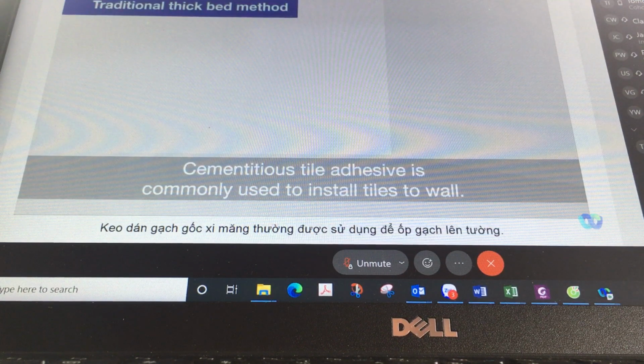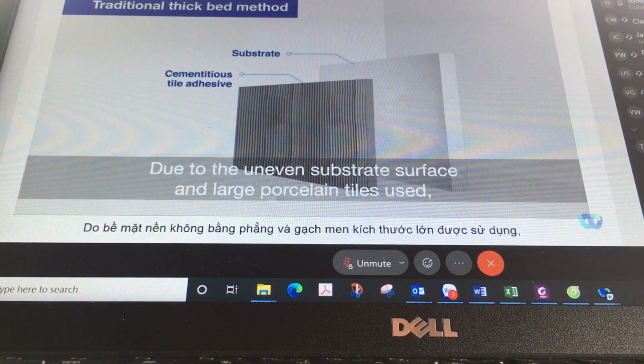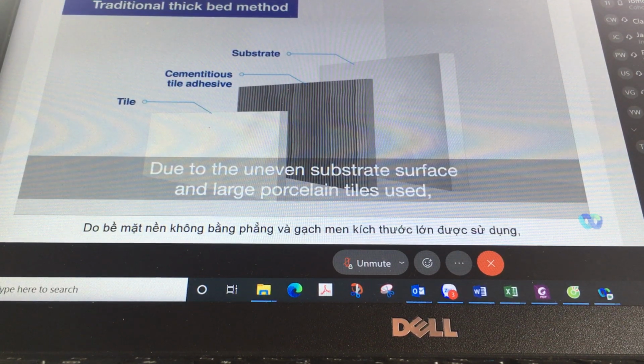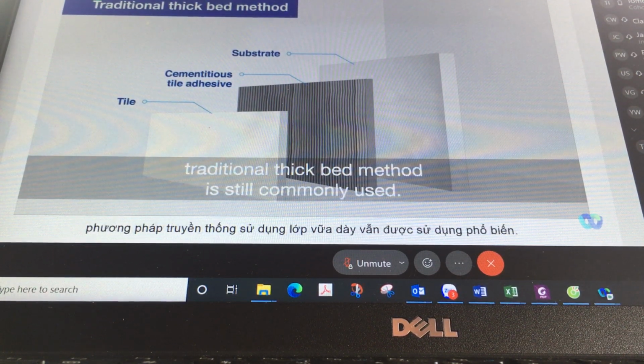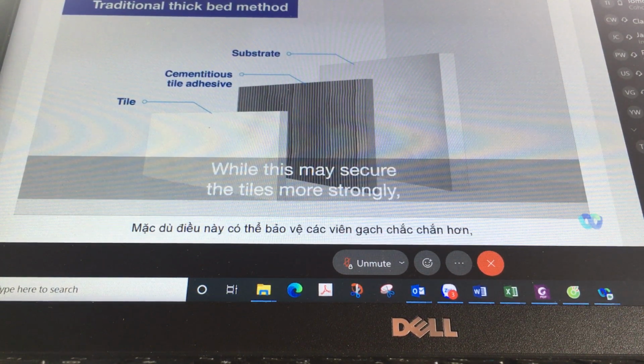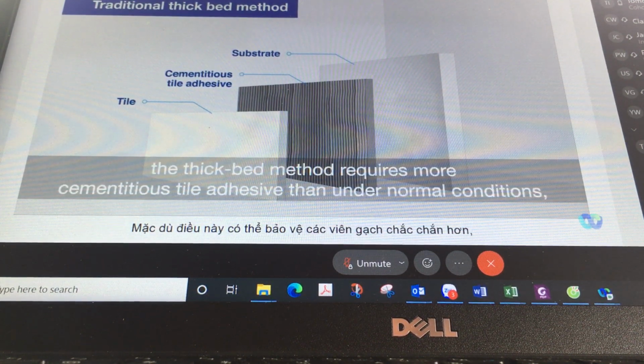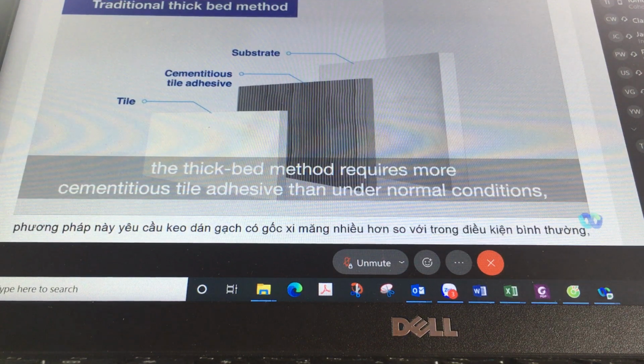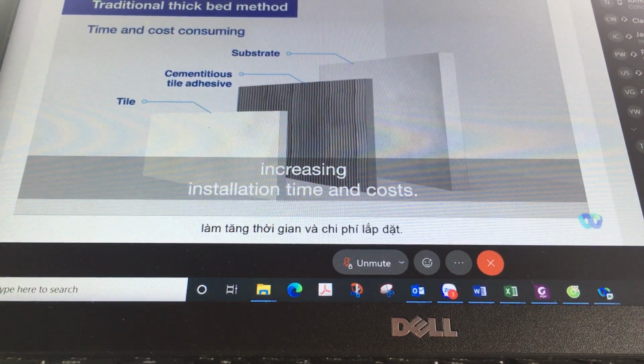Cementitious tile adhesive is commonly used to install tiles to wall. Due to the uneven substrate surface and large porcelain tiles used, the traditional thick bed method is still commonly used. While this may secure the tiles more strongly, the thick bed method requires more cementitious tile adhesive than under normal conditions, increasing installation time and costs.